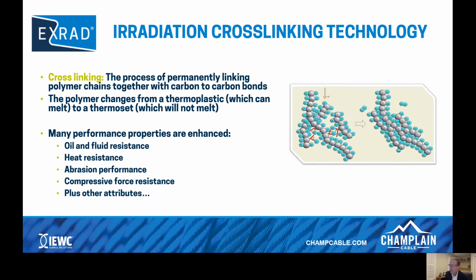So let's look at the diagram on the right. There are two polymer chains. The chain on the left is an uncross-linked chain. The polymer is randomly intermeshed, and if excessive heat is applied, it will melt. After cross-linking, you get the polymer chain on the right, where the hydrogen atoms that were attached to some of the carbons have been removed from the carbon, and that causes the carbon to attach to another carbon. And when it does so, it will never again release. It is cross-linked, and you can see it's a much neater arrangement of the polymer on the right, and you can see the carbon-to-carbon bonds.